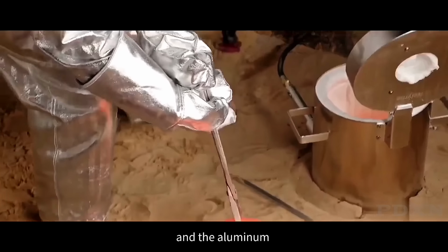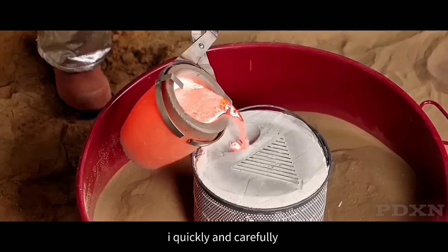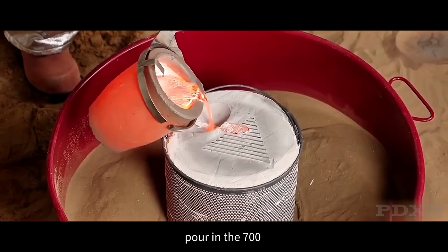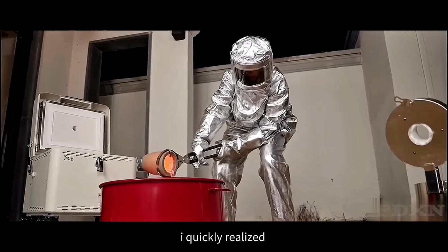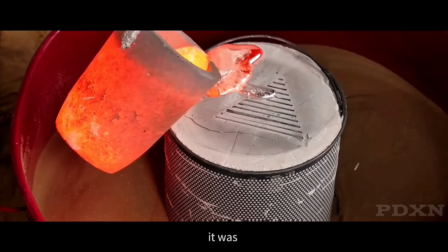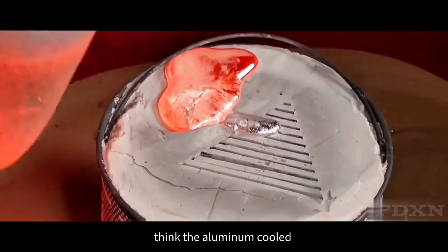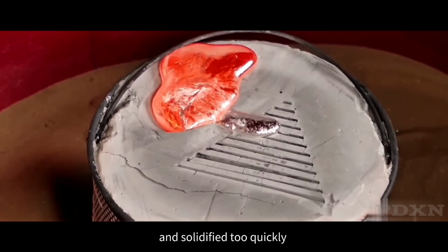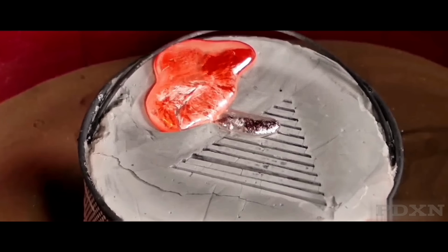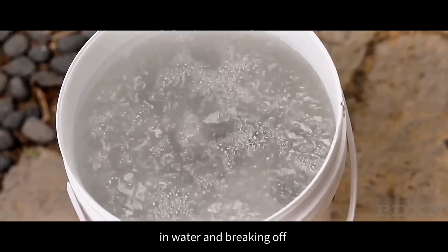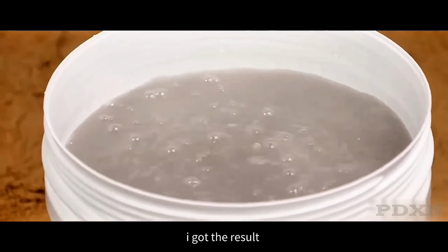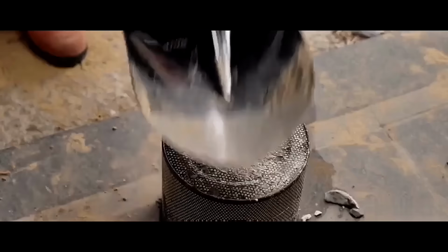While both the mold and the aluminum are still hot, I quickly and carefully pour in the 700 degrees Celsius molten aluminum. I quickly realized that about halfway through, it was getting a little hard to pour. I think the aluminum cooled and solidified too quickly, so the rest of it couldn't get in. After cooling it in water and breaking off most of the plaster, I got the result of my first casting.